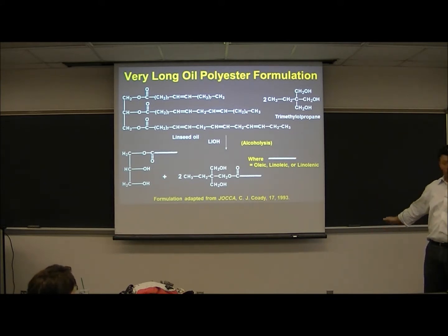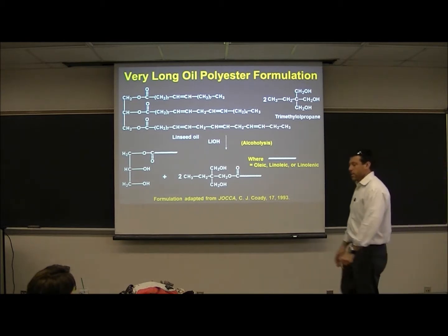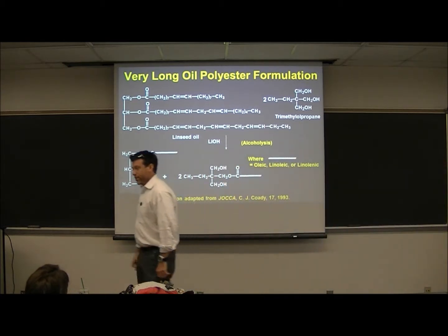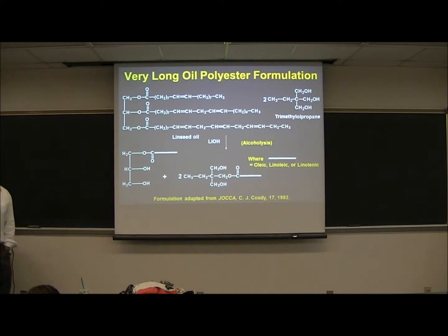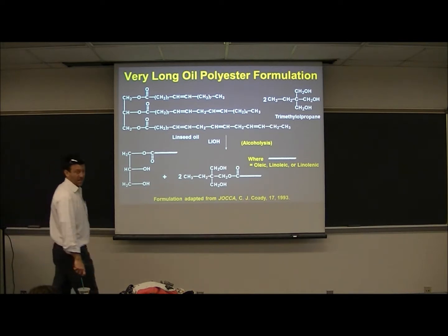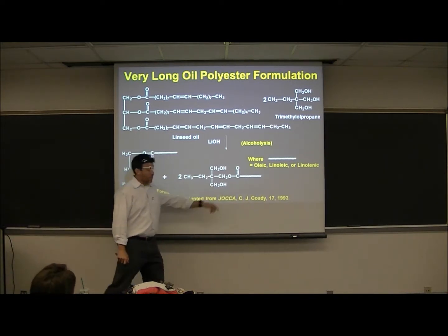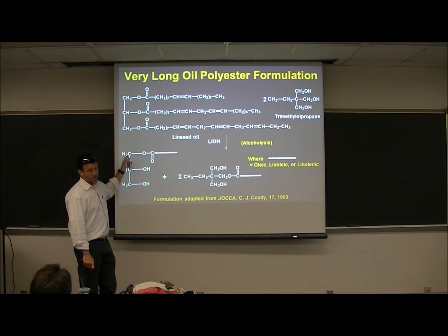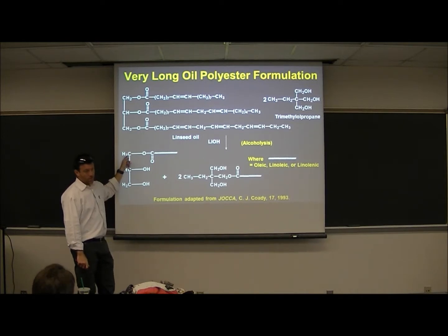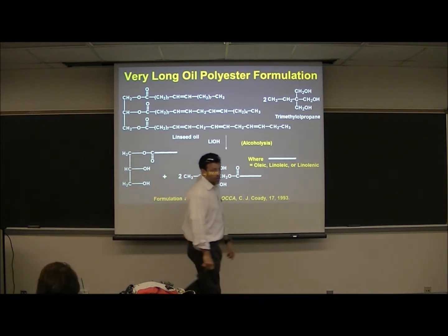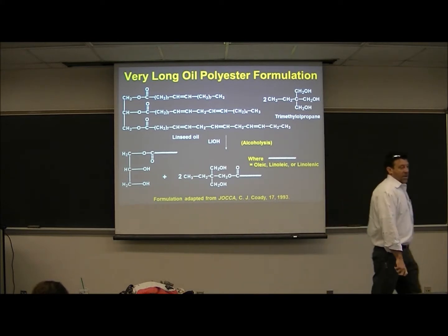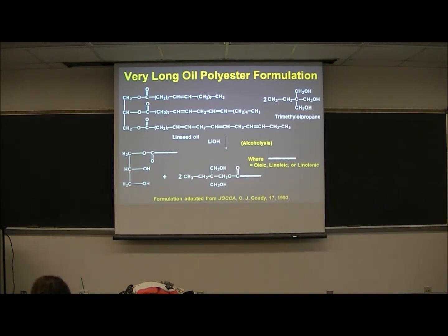Theoretically, none. This reaction turns out to be quite an interesting one in that, short of NMR, and it needs to be high resolution NMR, because they need to be able to tell the difference between that CH2 and that CH2 very definitively, which with a low resolution NMR you can't. With our 500 and 600 you can. This would be distinctly different than that in carbon terms. Turns out to be problematic with regards to how do you determine the extent and progress of the reaction.